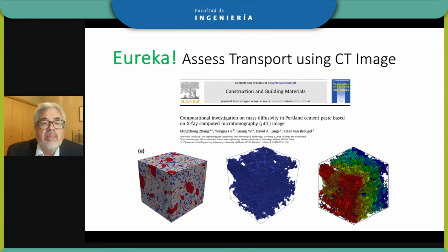Okay, so these kinds of images can now be used as a study of the transport of water moving through this microstructure. And so we had a paper working with partners at Delft University, where we were using hydration models and pore structure and bringing together our knowledge of the pore size distribution, the diffusivity of liquid species through the microstructure, and seeing if our microstructure matches up to other experimental results.